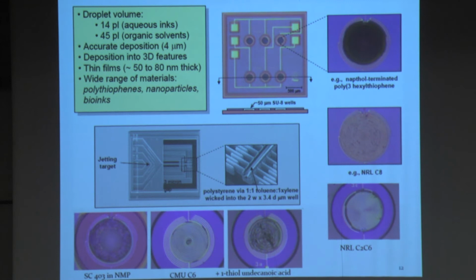Now, the capabilities are as follows. For inkjetting water, the smallest droplet possible is something that has 14 picoliters. For organic materials, normally you can jet from 45 picoliters and up, depending on the nozzle. This is the nozzle we use, of 30 micron diameter. Now there are nozzles up to about 100 microns in diameter available. Okay, you can see various examples of jetting.